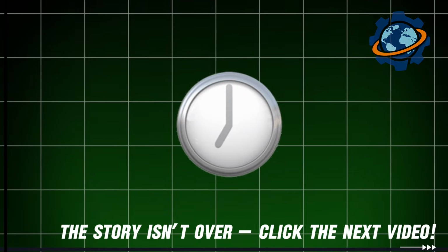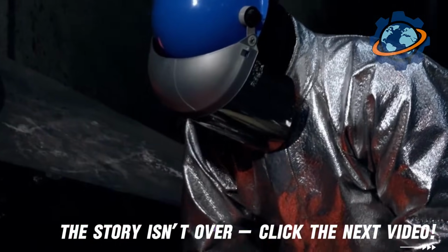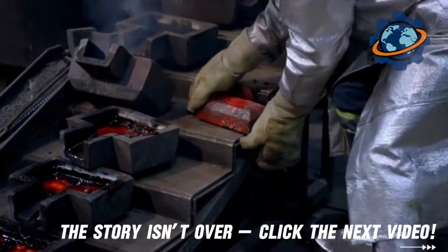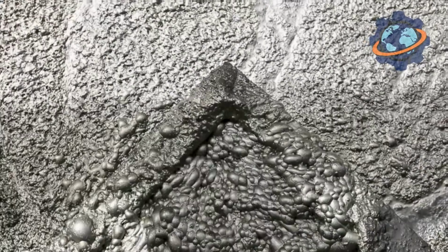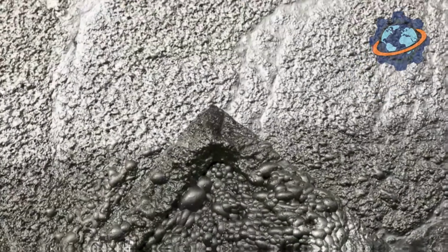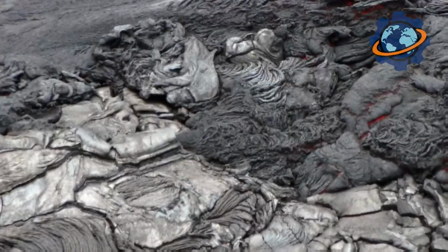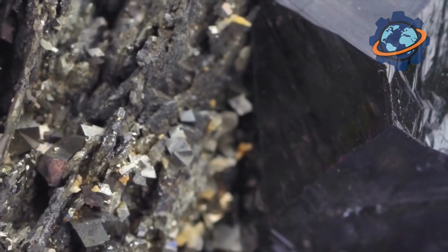This layer bonds permanently to the steel. On top, a layer of pure liquid zinc. The beam is held in the bath for 1 to 2 minutes. Then it's pulled out. Excess molten zinc drains back. In air, the coating quickly solidifies. The surface becomes silvery, matte, with the characteristic pattern of crystals, zinc flowers. Coating thickness from 2 to 8 thousandths of an inch. That's just fractions of an inch, but it's enough.